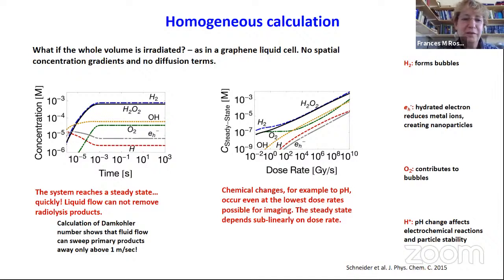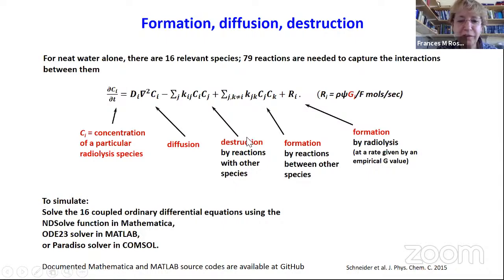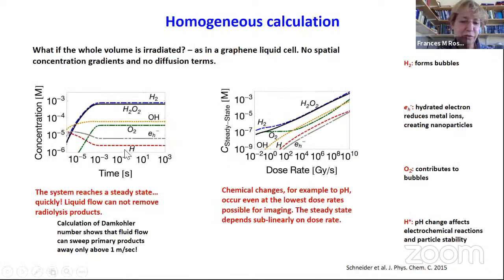So what if we illuminate the whole volume of liquid with the electrons, for example, in the little pocket in a graphene liquid cell? This is what happens typically. Look at the time range. All of these species started out with very low concentration. After some time, they build up to a certain concentration, depends on the dose rate, but they build up over less than a millisecond. So it's almost instant that the electrolyte goes to a steady state with a different chemical composition. And the reason it's a steady state is because all of these things are being destroyed and formed, and this happens until there's a balance, until the concentration of everything is correct to keep this in steady state. So a steady state forms.